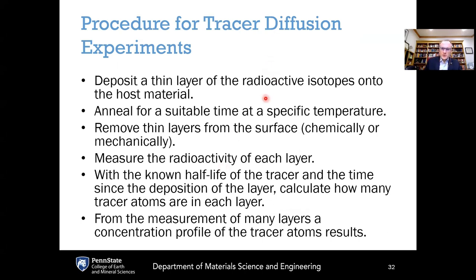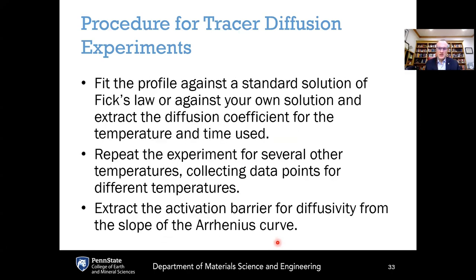The procedure for doing tracer diffusion experiments is first to deposit a thin layer of the radioactive isotope onto the host material. Then you do a heat treatment or annealing of the sample at a specific temperature for a given amount of time. Then you remove thin layers from the surface, either chemically or mechanically, measure the radioactivity of each layer, and using the known half-life of the tracer and the time since the deposition of that layer, you can calculate how many tracer atoms are in each layer as you remove them. And from these measurements of many layers, a concentration profile of the tracer atoms is obtained.